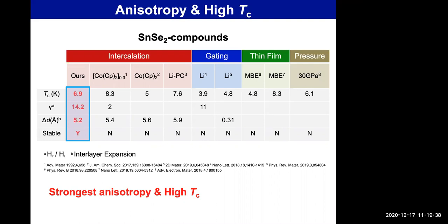People had found that if you have a heavy fermion compound, especially if you think of it in terms of spin fluctuation theory, TC would be lower in the isotropic compound. And when you do the measurements in a tetragonal compound, which is kind of semi-anisotropic, TC rises by a factor of 2 or 3, sometimes 10 times. So the question was, why would there be robust pairing in a quasi 2-dimensional structure as opposed to a 3-dimensional one? Could it be that the amplitude of the oscillations in the interaction is stronger because of low dimensionality?